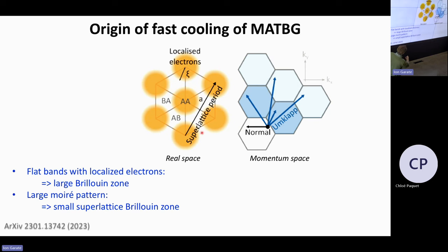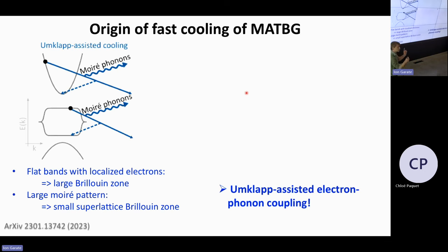So you have these different sites where you have these localized electrons, but your Moiré pattern can be tens of nanometers because your twist angle is just 1 degree. So you have a quite large superlattice period, which in momentum space gives you a very small Brillouin zone. So you have the large Brillouin zone from the localized electrons, but on top of that, the small Brillouin zone from the superlattice. And this means that you can have processes where you have these umklapp scatterings, where you couple outside of your superlattice Brillouin zone, and you can fold back, and by that overcome this huge momentum mismatch between the electrons and the phonons.